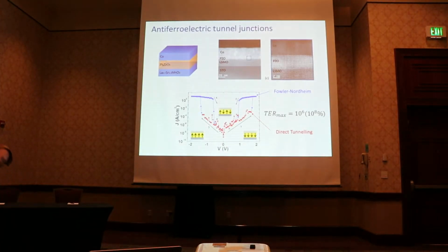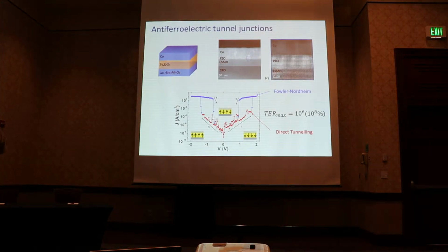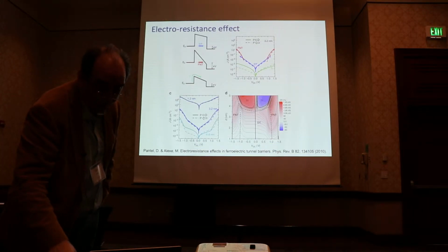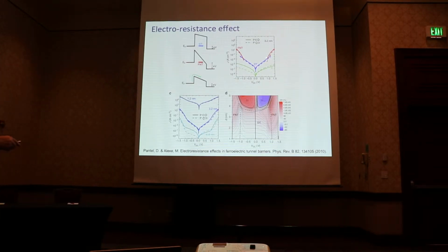We were thinking that that's direct tunneling, and that is just Fowler-Nordheim. It's just when we put polarization into the landscape, that lowers basically the barrier, and we enter automatically into the Fowler-Nordheim regime. So remember this one. So that was by applying a voltage.